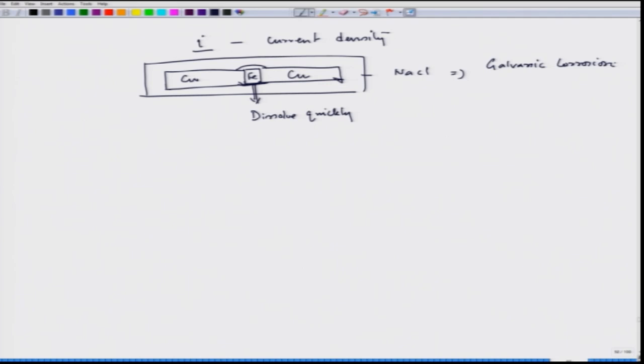And at that time we also considered the area effect. We analyzed this area effect, saying that if we have a higher cathodic area in connection to a smaller anodic area, then the dissolution of the anodic area would be faster than in a situation where the anodic area is larger than the cathodic area. The number of cathodic reactions taking place on the cathode area will be so high that, to meet that electron supply, more and more metal ions should form from the anodic region, and the dissolution becomes faster.